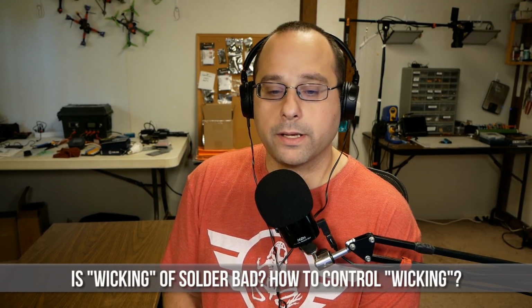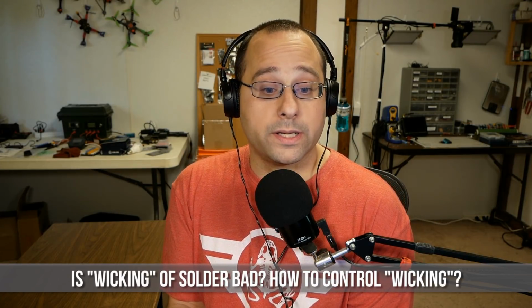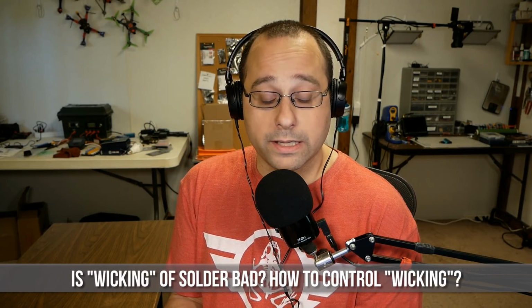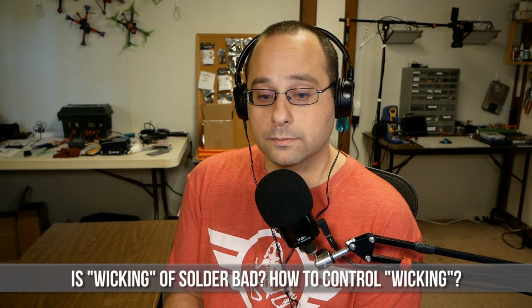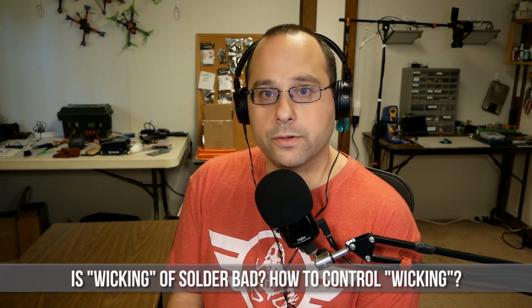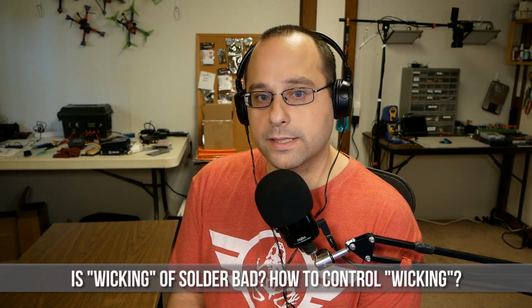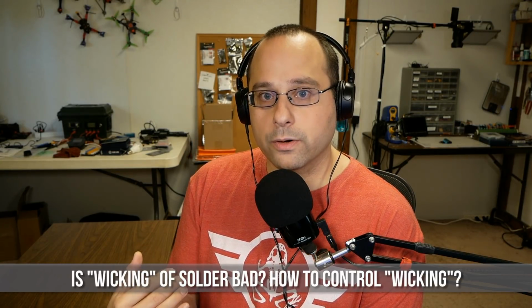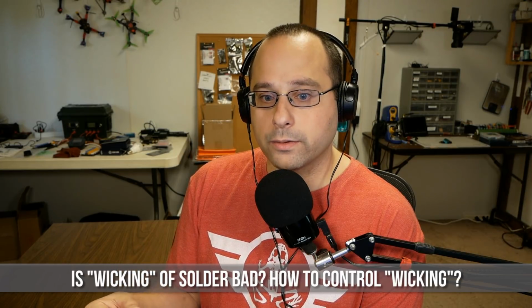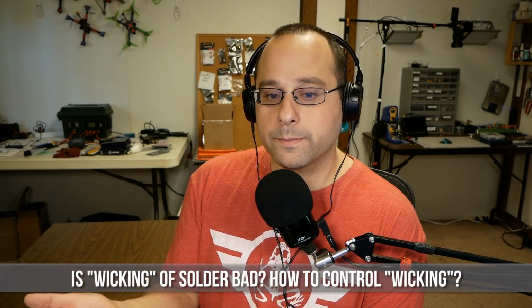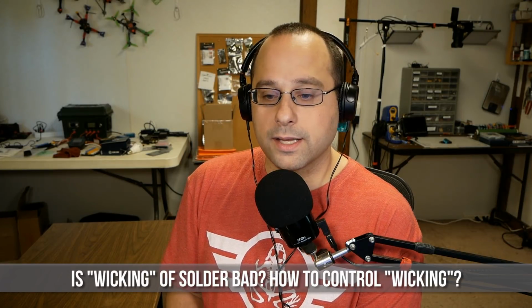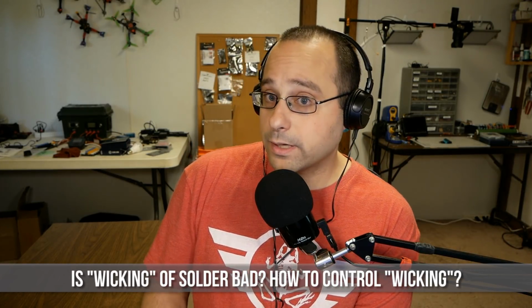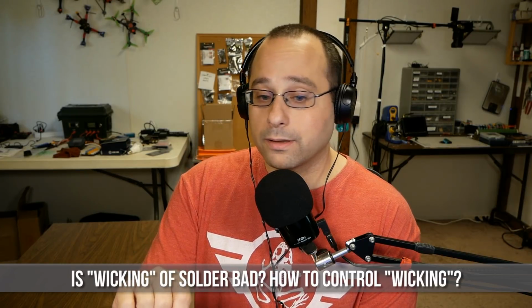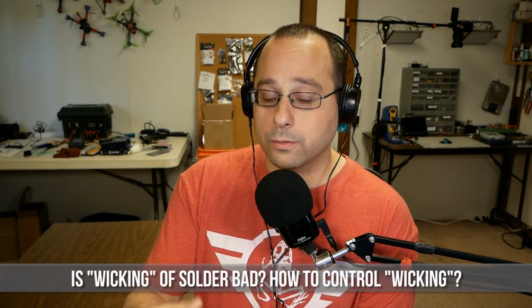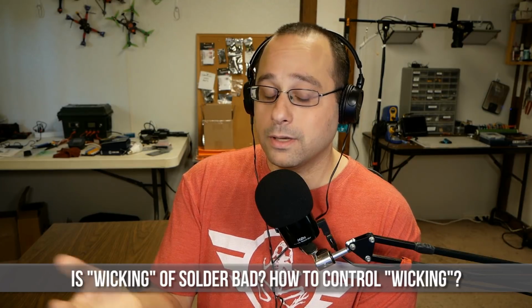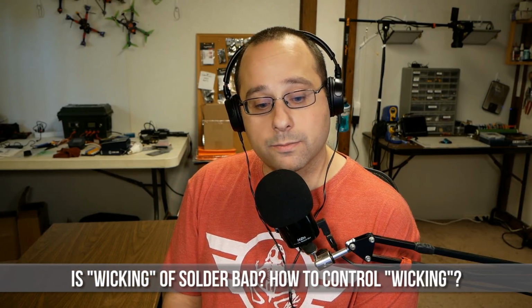Yeah, so there's nothing fundamentally wrong with it as long as you're okay with the wire being where it is, what you're saying? Correct. Yep. And a place we might run into that is if you're doing, especially with like a 4-in-1 ESC, where the wires are hanging off the edge of the board, a lot of times they'll be coming out the side of the quad. Well, you don't want them hanging out too much past the side of the quad because it increases the odds that they might get nicked or something. But for example, it sounds like if you were to bend them downward at like a 90-degree angle, and then if the solder were to wick up into them and harden them at that angle, as long as you're okay with that angle, maybe that's not such a big deal.